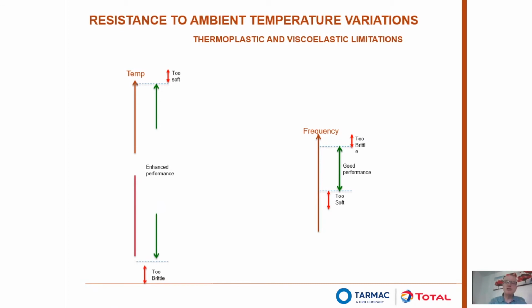And the contribution of the polymer means that we can stretch the frequency of force at which it becomes too brittle. The reality is that it doesn't do an awful lot to the bottom frequency force. In other words, with static forces, static creep, the polymer doesn't have time to recover, because elastomeric polymer impact is all about giving and then recovering, giving and then recovering. But if that force is constant in a creep type of situation, the polymeric impact doesn't have time to recover. So it does keep going. So with the frequency of force, it's very, very important at the high end, the high frequency forces.